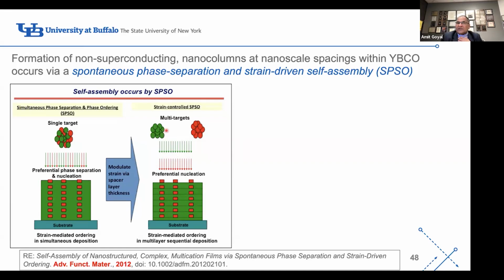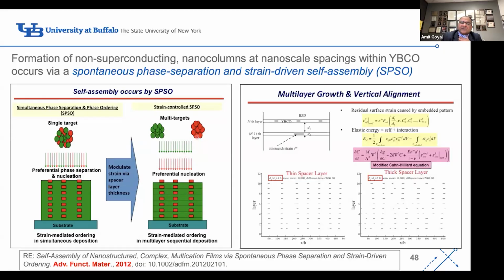We can understand the strain-driven self-assembly by taking 2 separate targets of the superconductor and the insulating barium zirconate, and we can create individual layers by varying the thickness of the spacer layer. So in this case, we deposit a mixture of the two, and then we deposit a layer of no barium zirconate containing superconductor. And then we can see at what spacer layer thickness we get alignment. We find that when the spacer layer is below a certain thickness, we get aligned nanodots. And hence if we do continuous deposition, we'll get a nanocolumn to minimize the strain. We studied all of this by what we call the modified Cahn-Hilliard equation from a phase separation perspective.